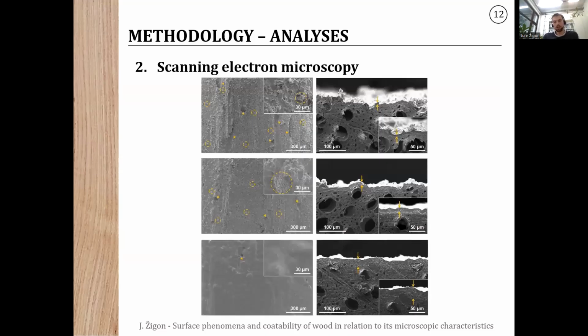Also using scanning electron microscopy on the coated wood. On the left side, we see three images from the surface, some artifacts, I won't go into detail too much. And on the right side, again, using it for measuring the coating thickness and, yeah, also the penetration depth.